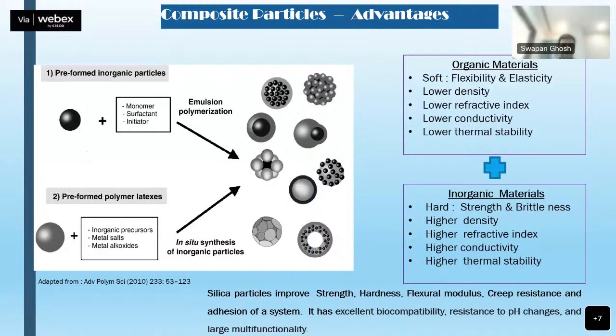The other part is that these silica particles are very important in that they provide very good strength, hardness, flexural modulus, and creep resistance, and they are very important when you think about adhesion. To improve the adhesion of a system, they are of great importance. And the good thing here is that silica is biocompatible, it is resistant to a wide variety of pH changes, and it is multifunctional. You can actually modify the silica particle and create different types of functionality. Based on that, a different set of composite particles can be made.